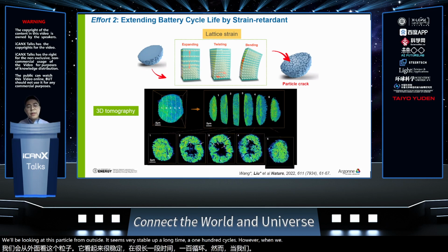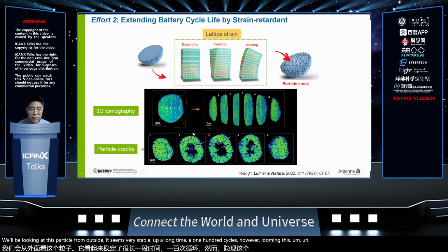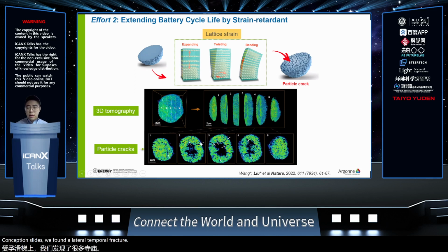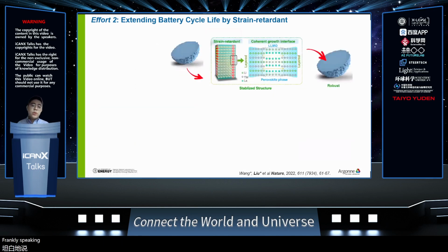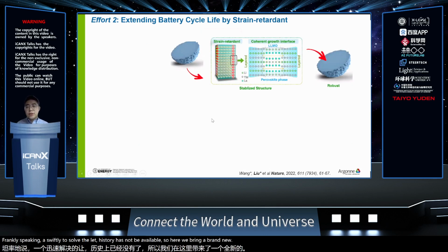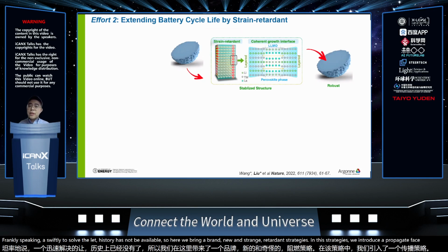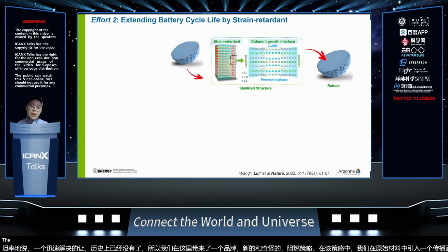In the picture below, I will show you how lattice strain damages these particles. When we look at this particle from outside, it seems very stable after a long cycle, 100 cycles. However, when we zoom in on this cross-section slice, we found a lot of particle cracking. Frankly speaking, a strategy to solve lattice strain has not been available. So here we bring a brand new strain-retardant strategy. In this strategy, we introduce a perovskite phase into the host material. The perovskite is structurally coherent with the host layered structure, but has a much more stable structural framework.